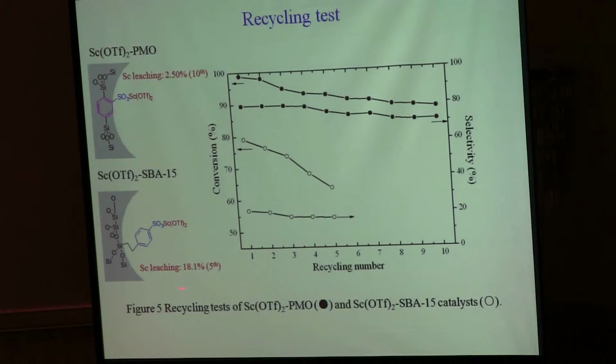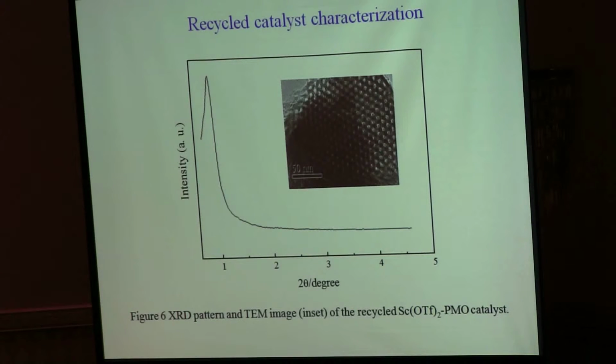So it means the scandium leaching is very high for SBA-15. And after reaction, we characterized the recycled catalyst. It also has an ordered mesoporous structure.